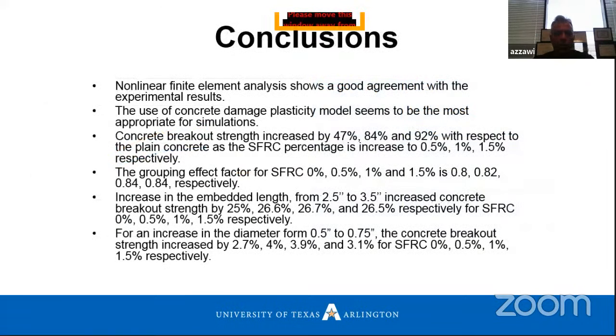concrete breakout strength. In general, I feel this is good research because it really goes and studies the effect of grouping action experimentally and also numerically, which is not mentioned in the ACI code. We also don't have numbers for how much grouping effect factor we have to use. But with this study now we have some values we can use. The nonlinear finite element analysis shows a good agreement with the experimental results, and the use of the concrete damage plasticity model in Abaqus seems to be the most appropriate for this simulation.